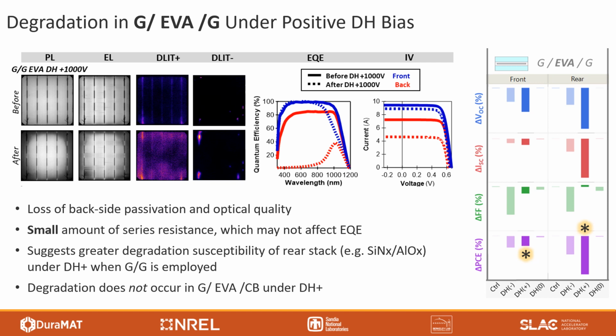Looking at the EQE, we see almost zero EQE for the backside at the short wavelengths that would be absorbed closer to the cell surface, and then increasing EQE as photons get absorbed more toward the bulk. This tells us that it's a problem with the backside recombination, and now we're just getting started with coring and microscopy to look into the possible corrosive process that could happen on the rear side.